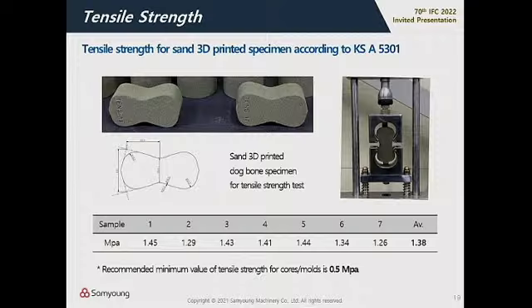And the third test is about tensile strength. We tested tensile strength for the 3D printed specimen according to the standard. This picture shows the actual 3D printed dog bone specimen for the tensile strength test. And this is the test equipment. The table shows the test results for 7 different specimens, and the average tensile strength is 1.38 megapascal, and the recommended minimum value is about 0.5 megapascal. So the result was much higher than that.